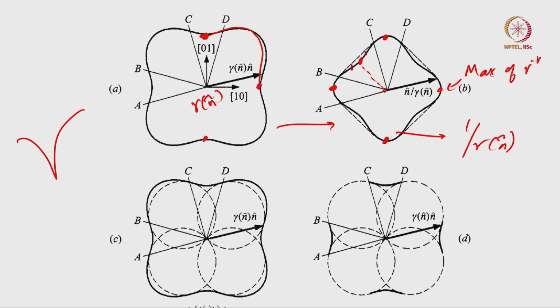So, what am I going to do? I am going to look at gamma inverse plot, and then I am going to draw a line between these two surfaces, and I am going to say that this point is actually inside this line. So, of course, this can split up into this surface and this surface. Then I ask the same question about this surface. Will this surface split up into some surface here and some surface here, and the answer is yes, because this point is also in between that line, inside of that triangle.